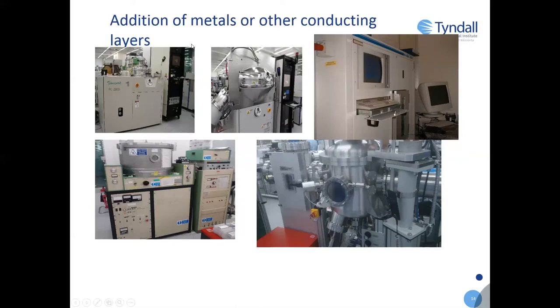So if we wanted to add conducting layers, for example, metals like we spoke about already, we have a suite of equipment that will do that again. We would have sputtering systems or physical vapor deposition systems. These are across the labs. The metals that you can deposit include copper, aluminium, and platinum. You can actually use sputtering also to deposit insulator. You can sputter silicon dioxide. The temperature of those tends to be either room temperature up to 200 degrees, so lower temperature than the PECVD processes.